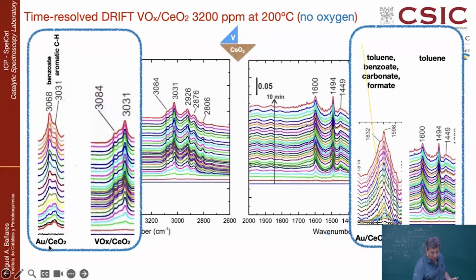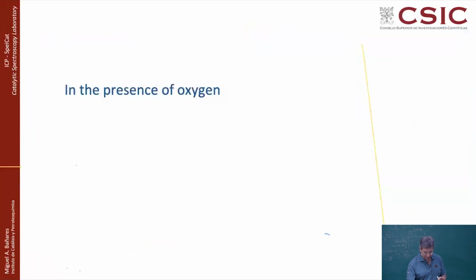However, when you're absorbing on gold ceria, very quickly, and this is like 5 minutes, at 200, everything goes essentially to the benzoate. So you see changes on the benzoate, you see changes here, so there is clearly oxidation without oxygen, 200 degrees C. Okay, what happens if I flow toluene and oxygen on this catalyst at the infrared operando system?